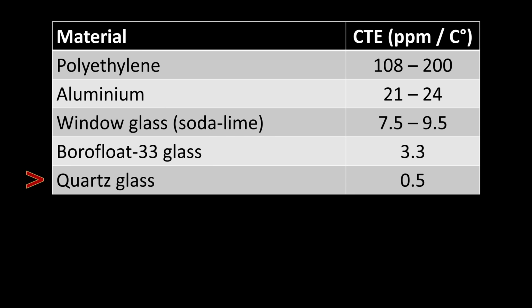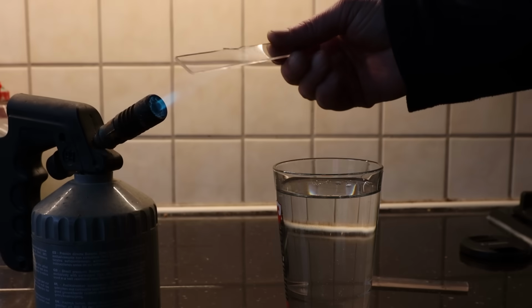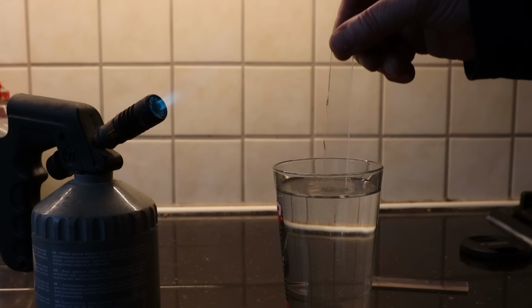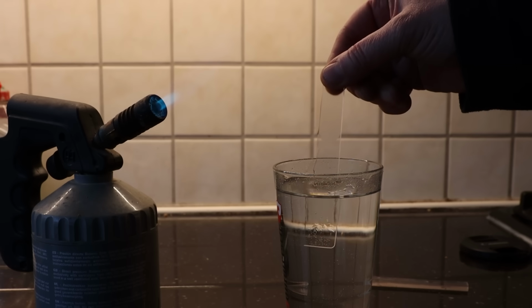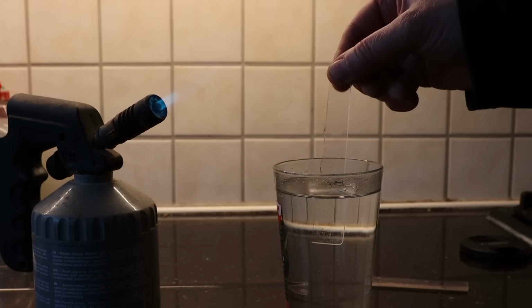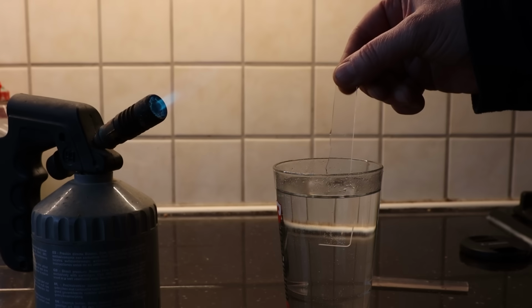And then there is quartz glass, which consists of pure silicon dioxide, which only expands by 0.5 microns per meter per degree Celsius temperature rise. So you see that even between glasses, there's quite a large difference in expansion coefficient. By the way, quartz glass is also particularly temperature shock resistant. Here you see me dip a strip of hot quartz in cold water, which also survives the treatment without breaking. And this again illustrates the importance of a low CTE.